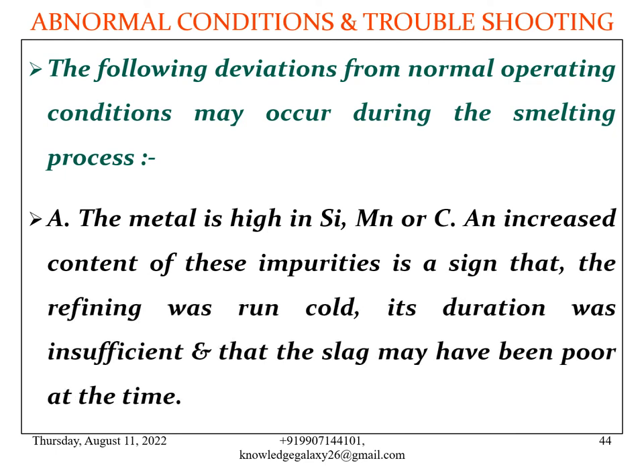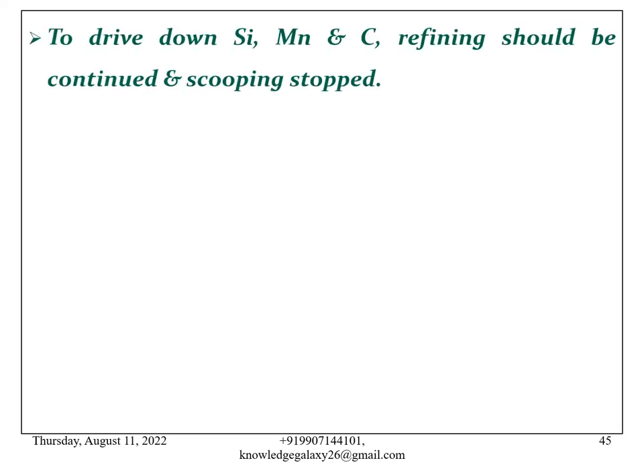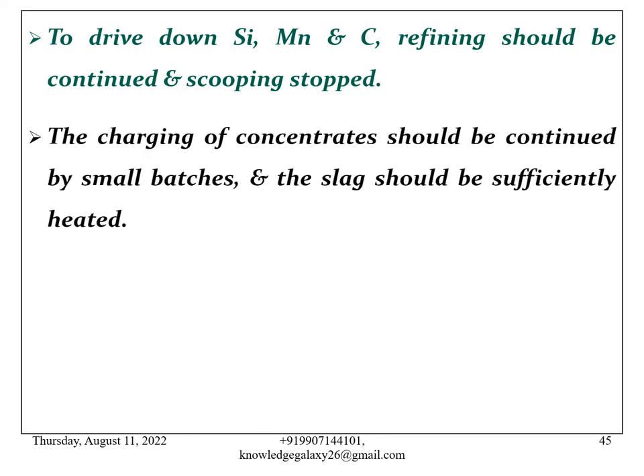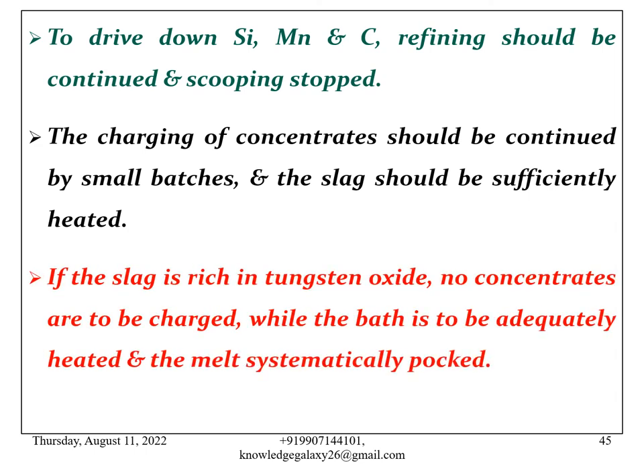First, the metal is high in silicon, manganese or carbon. An increased content of these impurities is a sign that the refining was cold run, its duration was insufficient, and that the slag may have been poor at the time. To drive down silicon, manganese and carbon, refining should be continued and scooping stopped. The charging of concentrates should be continued in small batches, and the slag should be sufficiently heated. If the slag is rich in tungsten oxide, no concentrates are to be charged while the bath is to be adequately heated and the melt systematically poked.